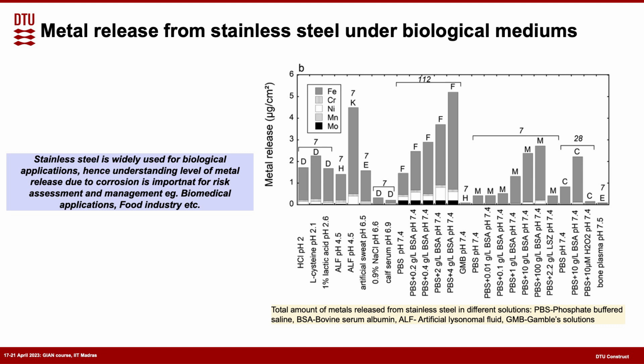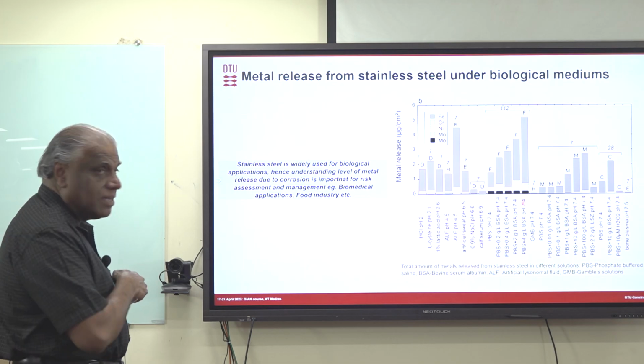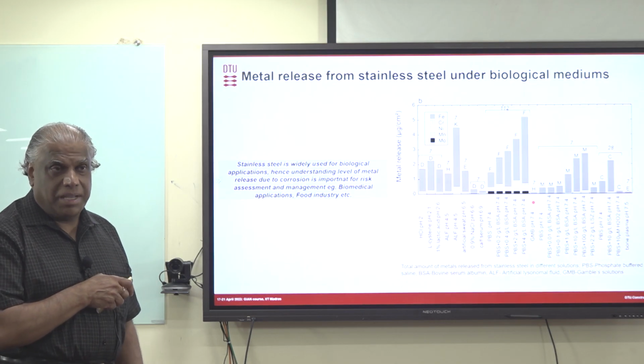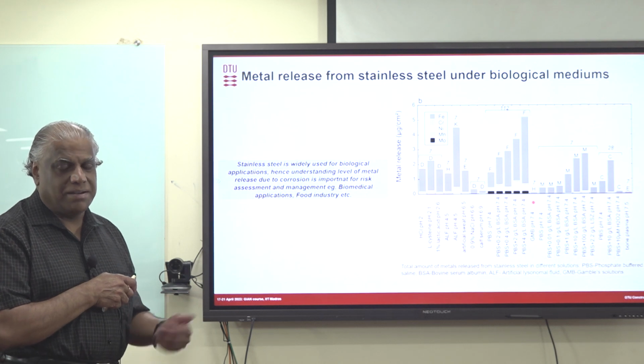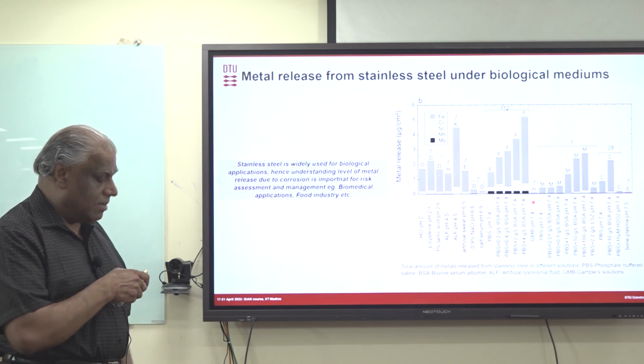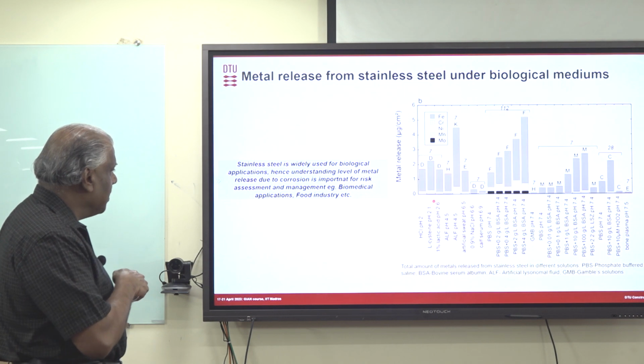The interesting thing for us is that you can see that iron is dissolved more in all these cases. That's understandable because these are iron-based alloys. And you can see that a little bit of chromium is also dissolved in all these cases. You can see this gray color part. Chromium is also dissolved. More interesting is the nickel release. For example, nickel is a very allergic material, and many people get metal-related allergy, and nickel is one of the really allergic materials. So that's very, very important.